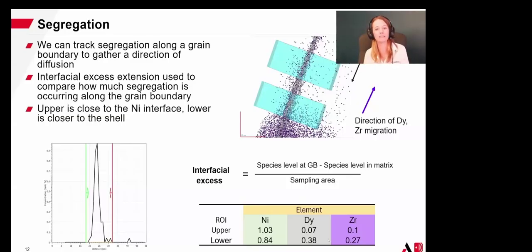Now we can repeat this analysis of interfacial excess for these other dopant atoms that we see, so dysprosium and zirconium. And we see that these are segregating more strongly closer into the matrix. Again, not that surprising, but if we look at these different directions, we see that the nickel may be diffusing down from the top from our electrode region, and our rare earths might be diffusing up along the grain boundary. So that's going to give us a little bit of an insight into how things might be moving or migrating inside these core shell structures.